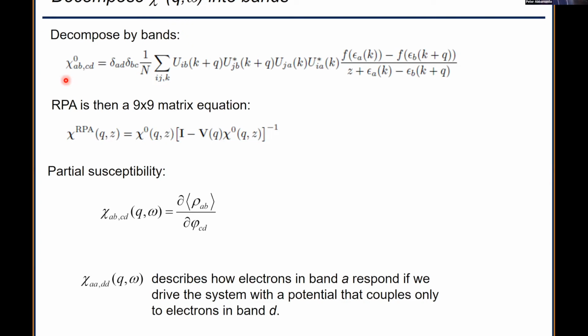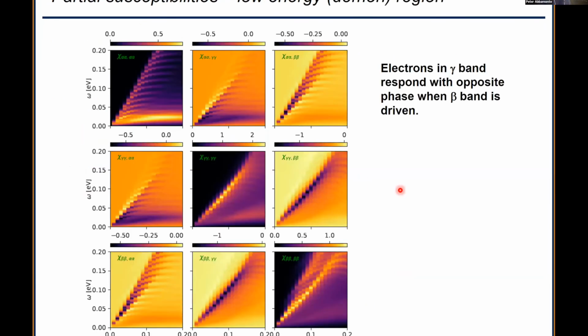But it's possible to do a band resolved chi and ask, how does the charge in the system respond if I drive it with the potential that couples only to one of the bands? So I could somehow invent a fictitious driver that just drives the beta band and ask, how do the gamma band and the alpha band respond due to that? And that allows one to define some partial susceptibilities. And what they look like is quite compelling.